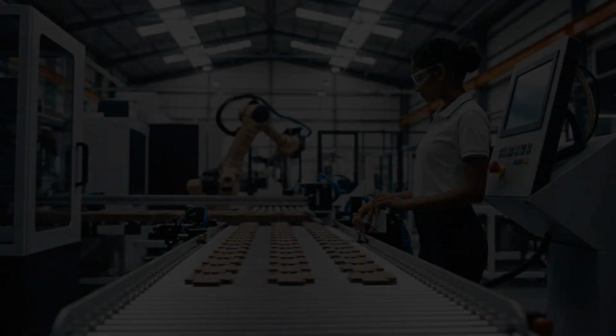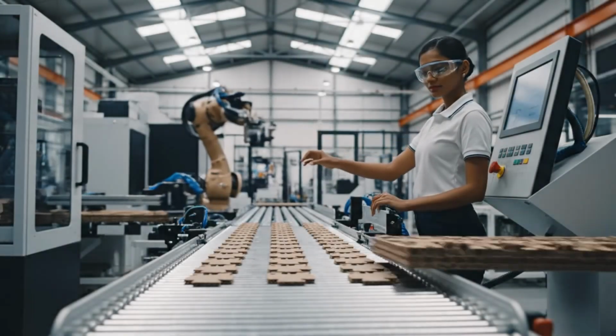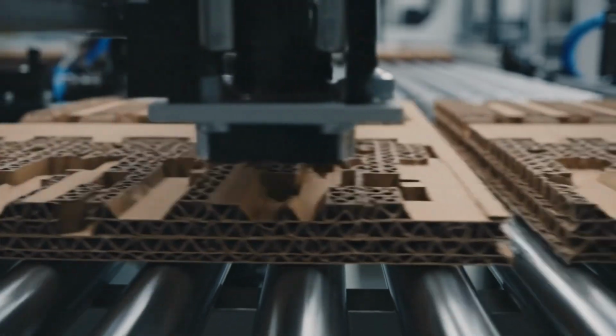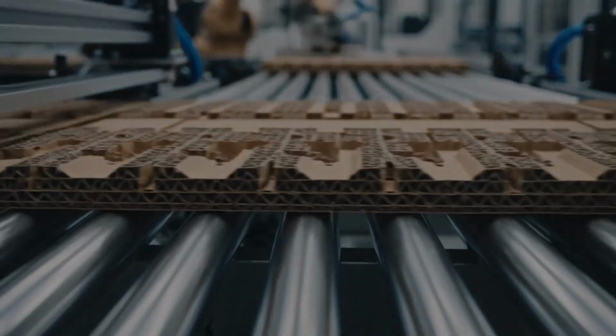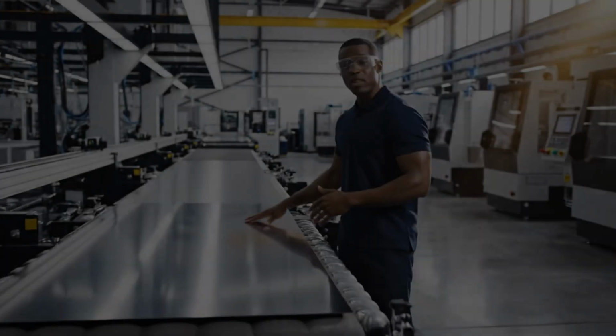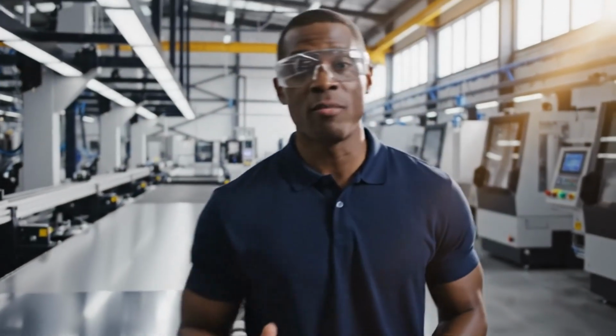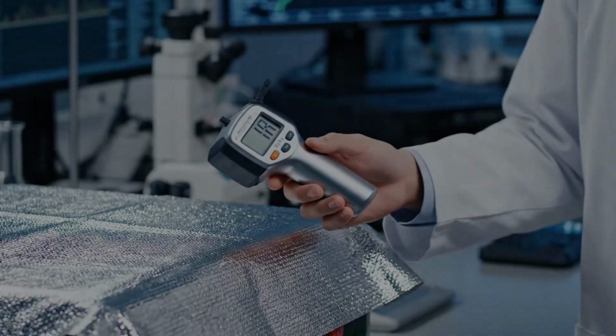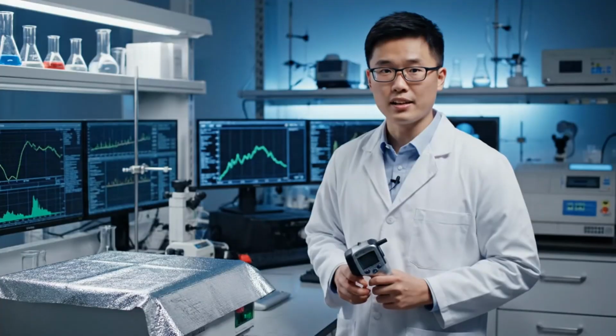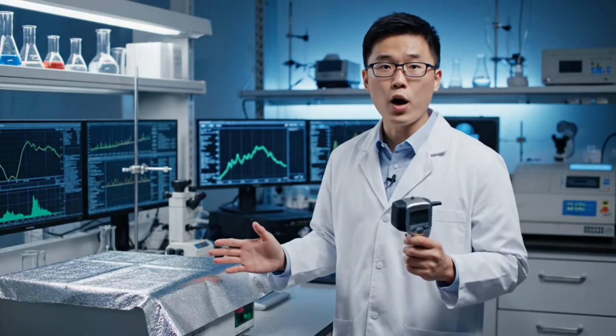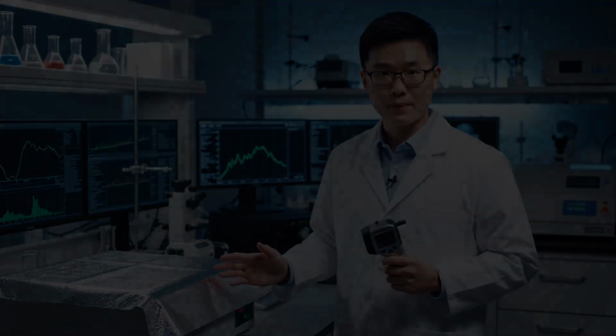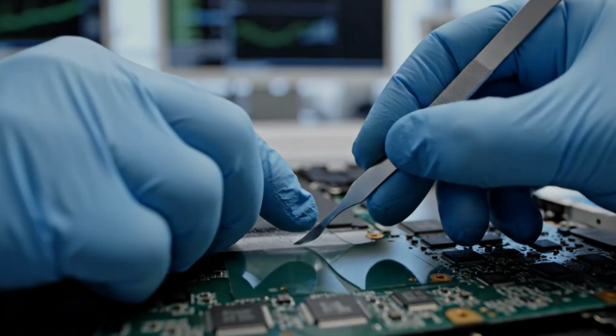Magnetic sensors continuously measure the coating thickness to ensure every centimeter meets the standard. This coating is the first line of defense against heat and weather. But to keep the sheet metal truly cool, a second layer of protection is needed, a special high-tech paint. This is the secret to keeping roofs 5 to 15 degrees Celsius cooler than regular corrugated iron.